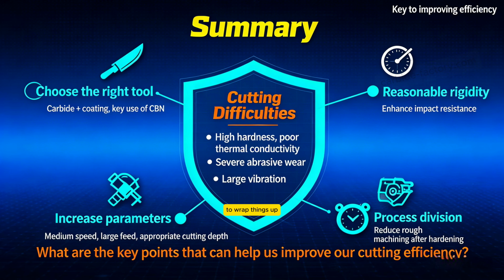To wrap things up, what are the key points that can help us improve cutting efficiency when dealing with these difficult-to-machine heat-treated materials? The core lies in 3 points. First, select the appropriate tool material and coating based on the material's hardness and abrasive wear characteristics. For instance, use cemented carbide paired with high-performance coatings or opt directly for CBN tools. Second, establish appropriate cutting parameters. Generally, it is recommended to use a moderate cutting speed, a larger feed rate, and an appropriate depth of cut.